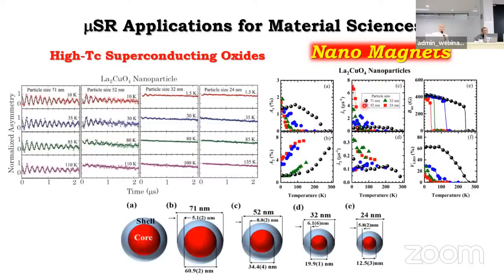So this is nanoparticles. Nanoparticle is not so easy to be studied by neutron, but muon can pick up the magnetic ordered state. And also, as you can see, the magnetic ordered state separated into two, the core state and the shell state. So this kind of volume we can simply sense by using muon. Neutron cannot sense at all, but muon can sense volume fraction or ordered state. This is a strong point of muon. So if you're interested in volume fraction or a magnetic ordered state, only muon can give you the answer.